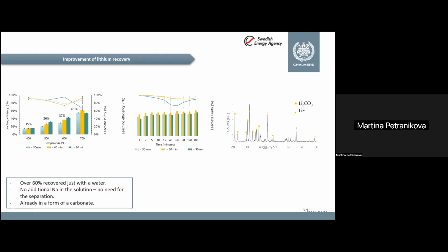But what is positive about this approach was that the main elements which were leached were just lithium and then a little bit of aluminum. And then we looked also at the product, what we could recover, and we recovered lithium carbonate. It was mainly this, and then a little bit of lithium fluoride, because of course we have some fluorides in the system. So then lithium will likely bind to the fluorine as well.